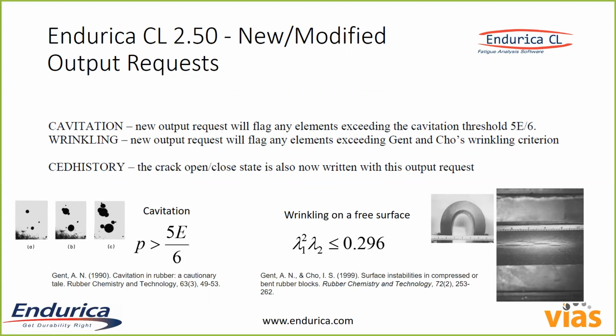Similarly with wrinkling, this happens on free surfaces where you have compression. We're using the criterion that was published by Gent and Cho back in the late 90s to check for surface wrinkling and give you flags when that might be happening. Finally, there's an output request that can tell you the open close state on a crack, right? As we're doing a critical plane search, Endurica knows the time history of basically every crack and every orientation. And if you want to know when the crack is open or closed, you can say, hey, tell me that. And it'll give you a time history of what the crack state is.